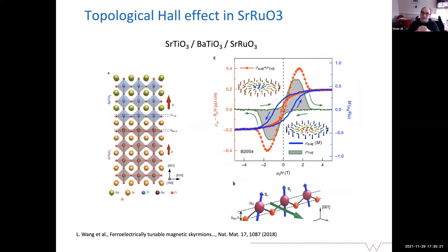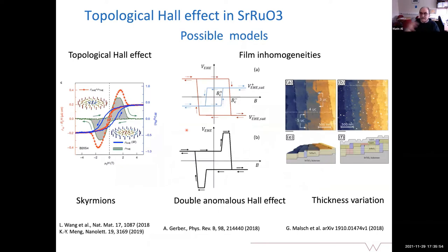Anyway, the interesting work which drew my attention was given by Tae Won Noh's group in Seoul, who discovered this topological Hall effect of strontium ruthenate on barium titanate. And that's very interesting because he mentioned that the skyrmionic phase in strontium ruthenate should occur due to the barium titanate, due to the fact that polarization will extend into the barium titanate. There is a controversy now in the literature, which says that it is actually not the skyrmionic phase doing that, it is just inhomogeneity in the thickness. And that gives an anomalous Hall effect with two different amplitudes and two different chiralities, so to speak, in this hysteresis, and that will result in this anomalous Hall effect.